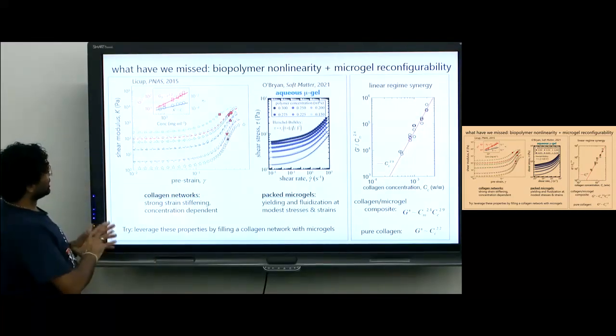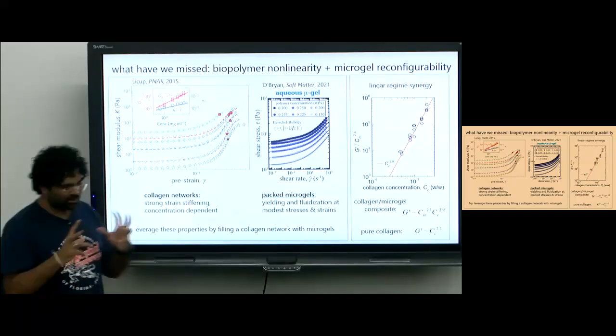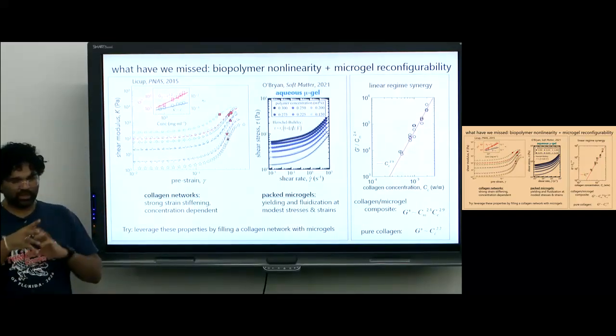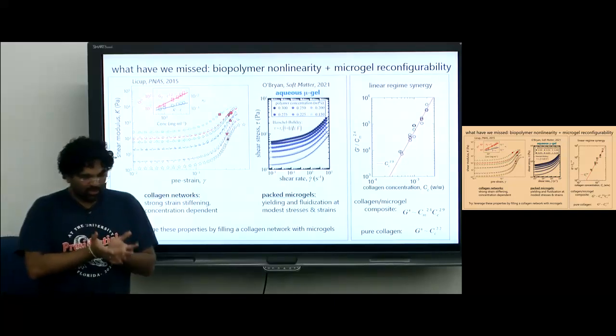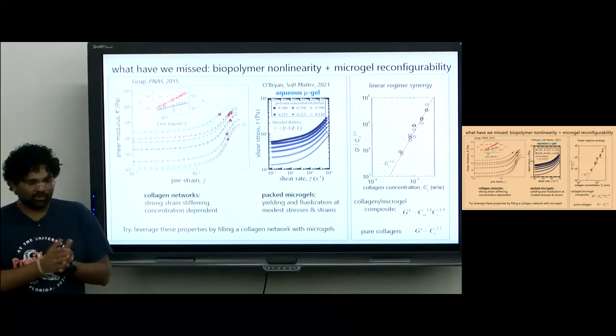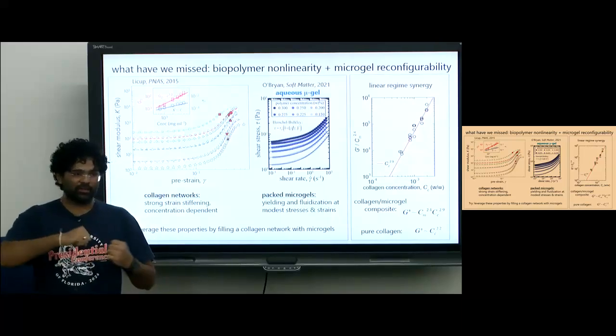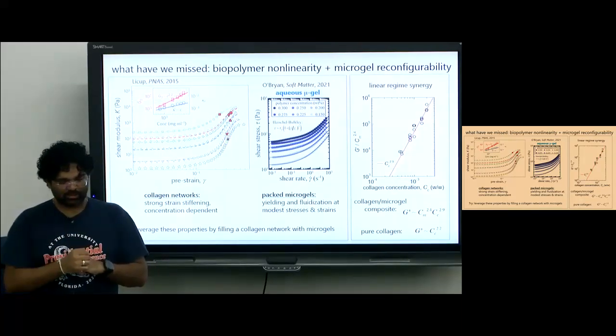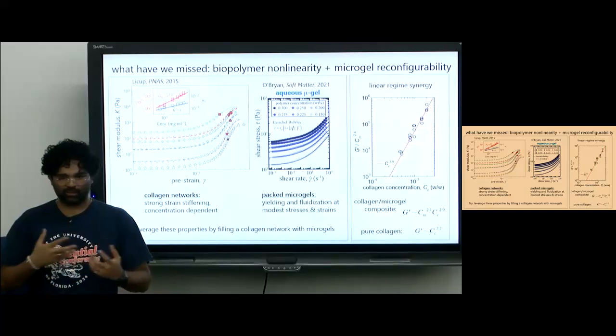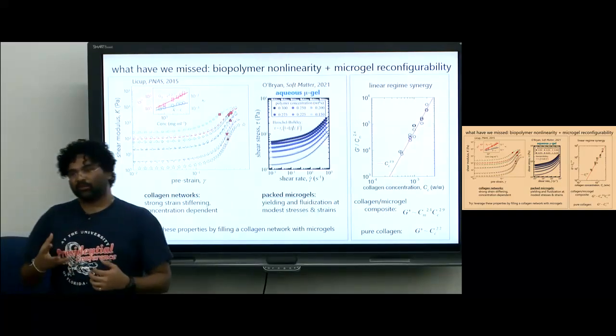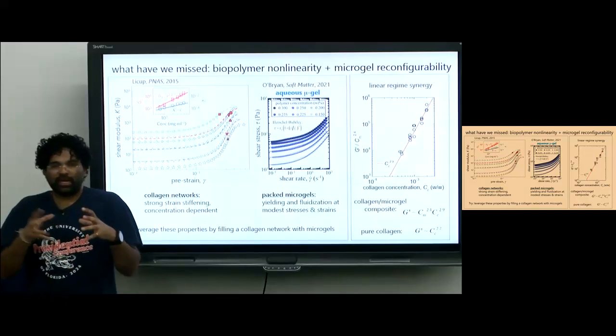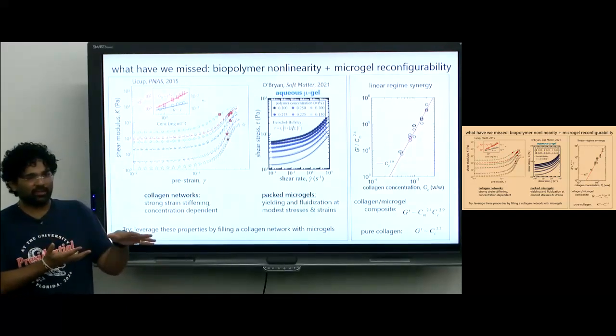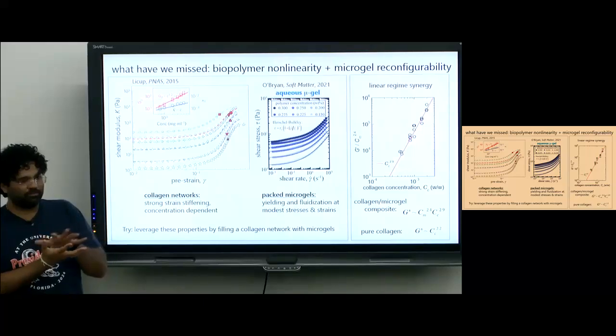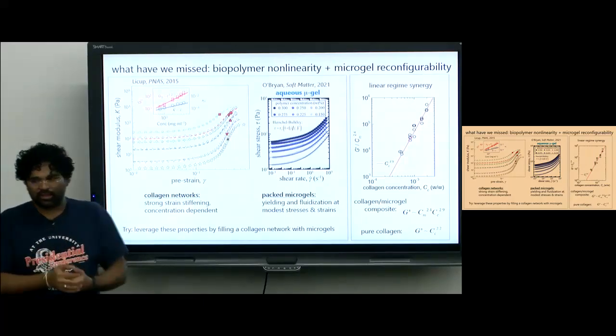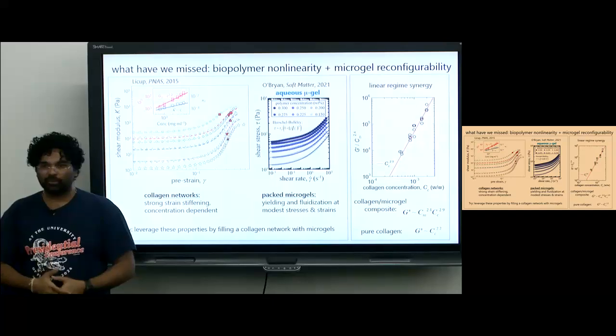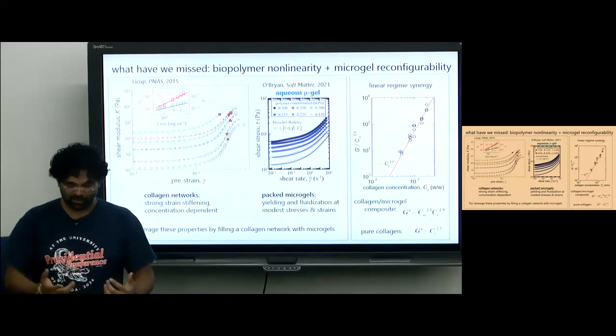Essentially, the idea is to combine the nonlinear behaviors of biopolymers with the reconfigurable nature of microgels. Biopolymers like collagen are usually known to stiffen. If you just strain them, they stiffen, and that is considered a nonlinear behavior in terms of the mechanics. The reconfigurability of microgels, meaning it's just a pack of spheres: when you shear them, they don't really get destroyed or stiffened, but the pack of spheres just rearranges, and we call that reconfigurability. And here we are putting those two together to make these composite materials. And like I said,